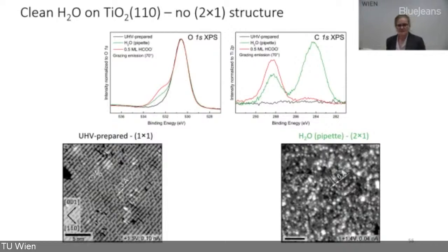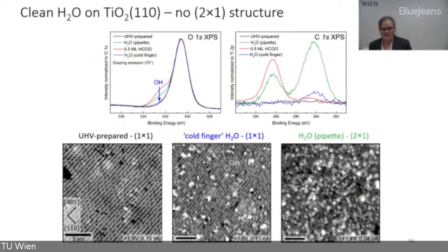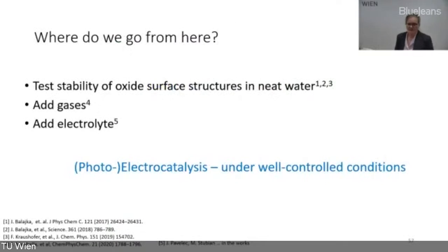So this is the same results I showed before. First clean, then after the pipette, and then when I do the same thing with what we call the cold finger, we have a very clean way of putting this water on the surface without contaminating it, where we can even do atomic resolution STM afterwards. So we go from there.